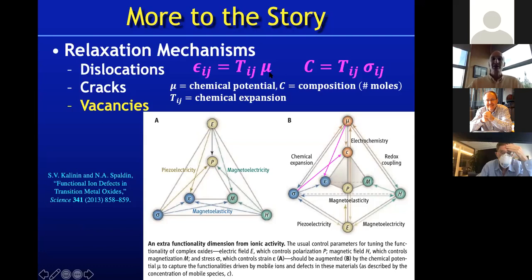So there is such an effect, and I'll show you a direct effect. So you change the chemical potential, maybe you change the pressure, change the oxygen partial pressure. So that would change the oxygen chemical potential. And by doing that, the material might react by forming oxygen vacancies, and having a lot of vacancies in the material might affect the shape of that material. So I can talk about a strain that comes from changing the chemical potential.